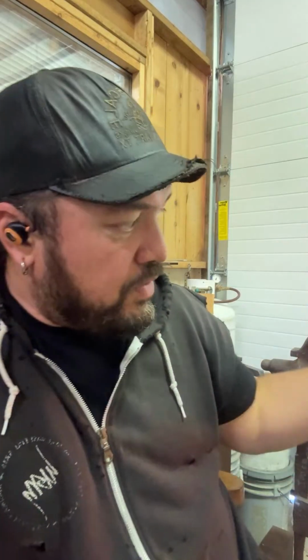But it leaves behind a soot, and that soot is free carbon, and that will more readily reduce the oxygen between the layers of the steel. But it ultimately comes down to the carbon getting hot enough so that not only is it moving around within that steel, but also off-gassing and leaching out of that steel to create that positive pressure between those layers, so that there's no more free oxygen. Within the forge chamber, for the fuel in the forge to burn, there has to be oxygen available, right? It's actually drawing oxygen in, but that carbon depletion between those layers is creating enough positive pressure that no fresh oxygen is getting in.